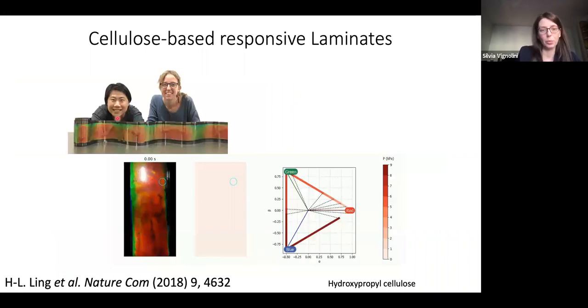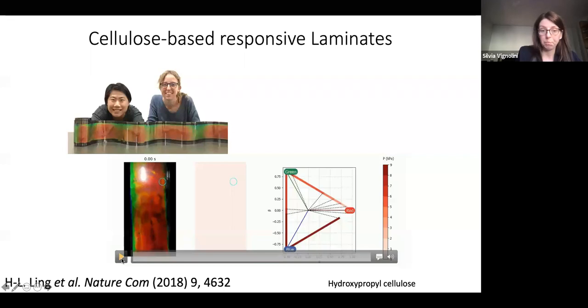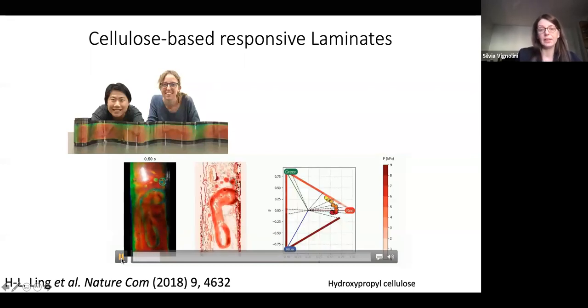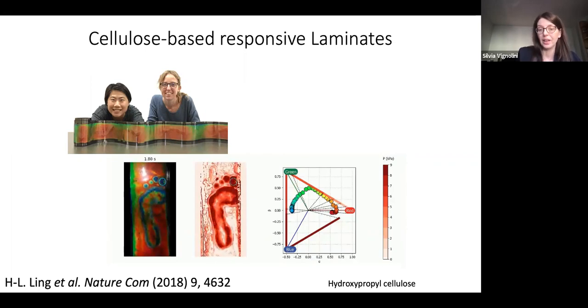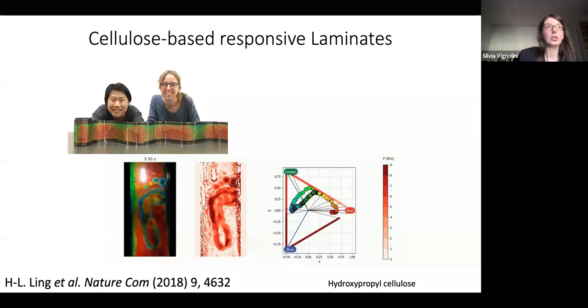And what is nice is that, and these are the two persons that worked on this paper, if you use them while they are still in the presence of water, you can actually exploit them as a sensor material. So this is a fully edible cellulose derivative, where you can make pressure devices. You can walk on top of this film and get a direct colorimetric response that, once you calibrate it to a value of a specific pressure, you can exploit to make a 2D map of pressure. The big advantage is that the material inside is so biocompatible, edible, and it's a cellulose derivative that doesn't cost essentially anything. So I think it's pretty cool.